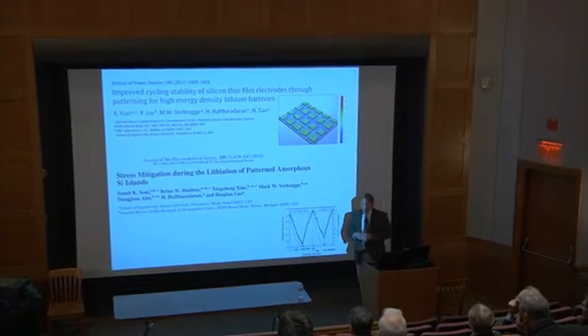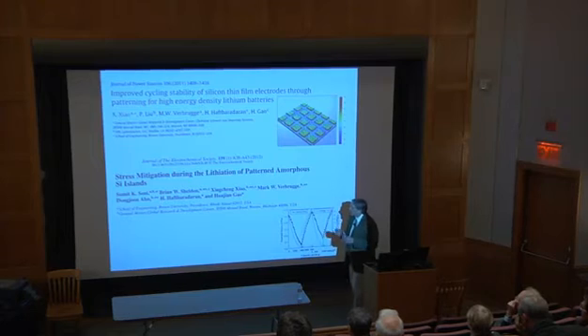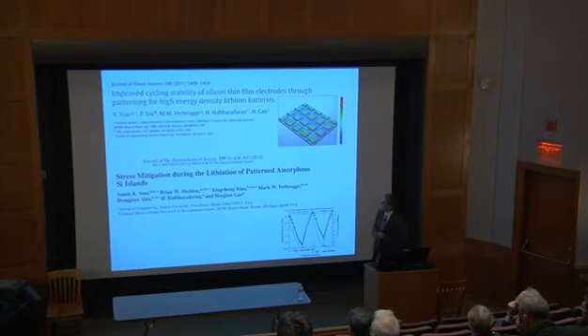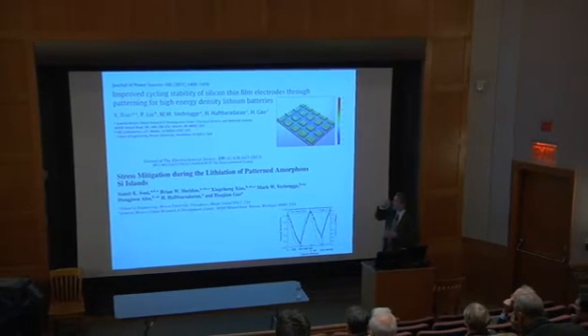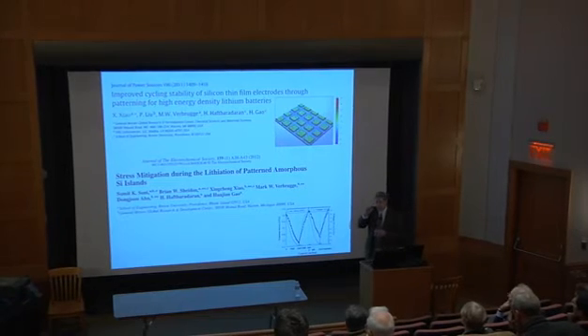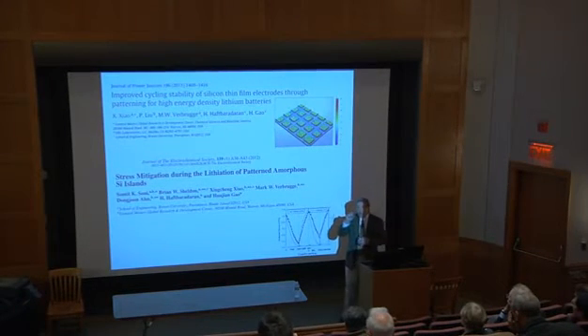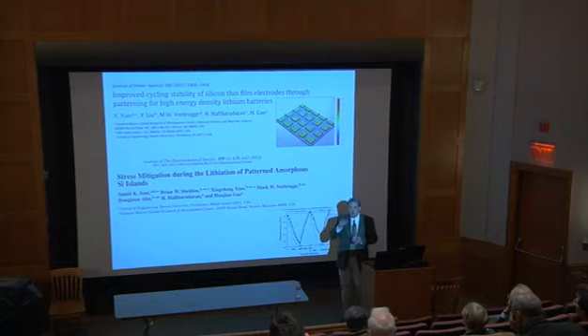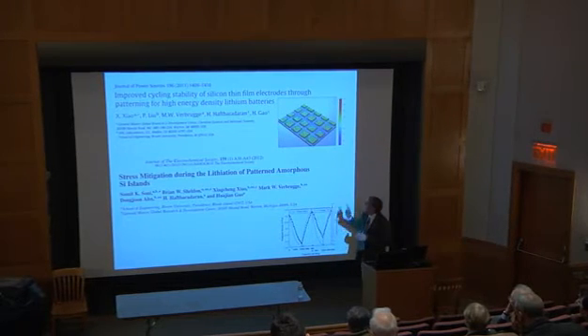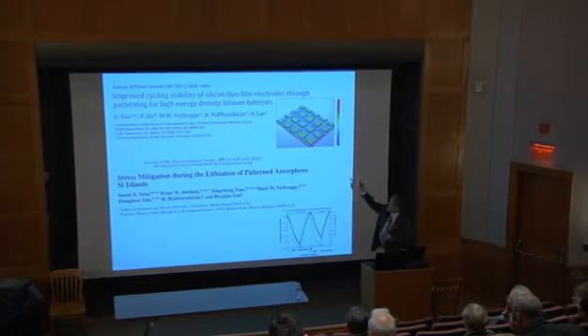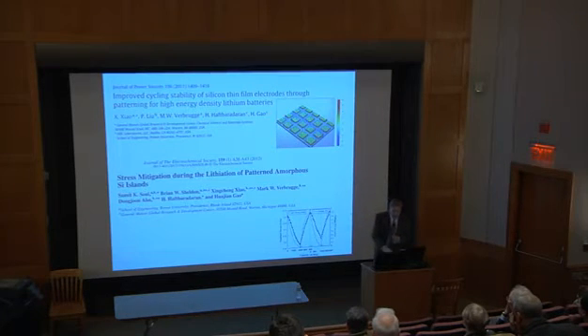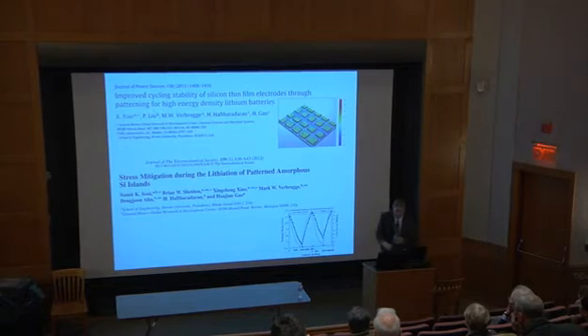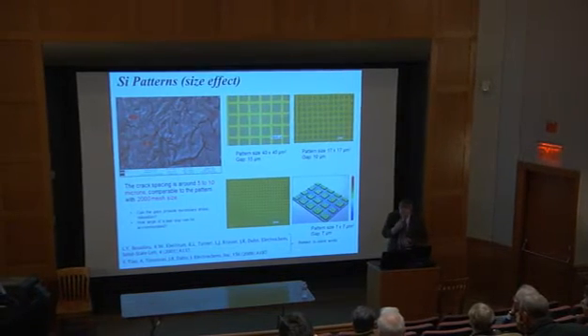So with Brown, we did some work on trying to measure stress in these systems. One of the things we did was to look at thin film, so we get a size effect here. We're going to go to very thin, 75 to 100 nanometer thick film, so we have some adherence to the substrate. And we put in stress relievers between the pads. These are pads of silicon on an otherwise inert substrate. And then we measured the stress, and I'll talk a little bit about that.